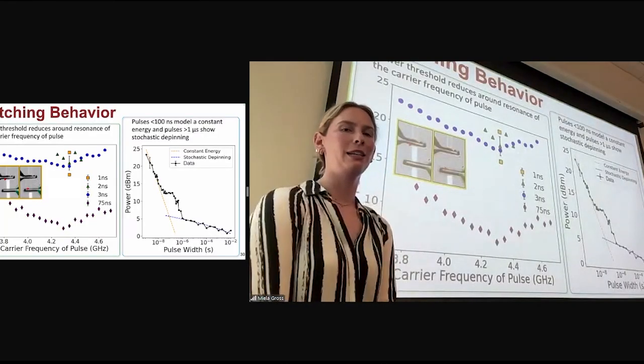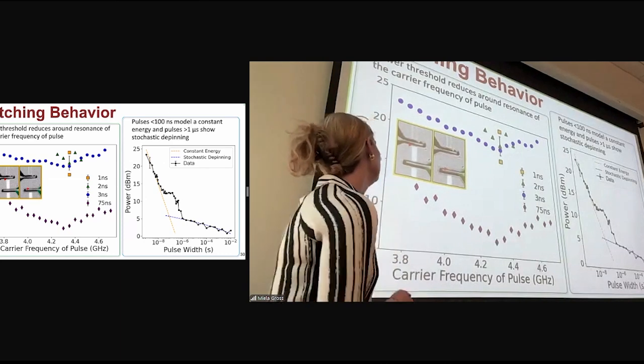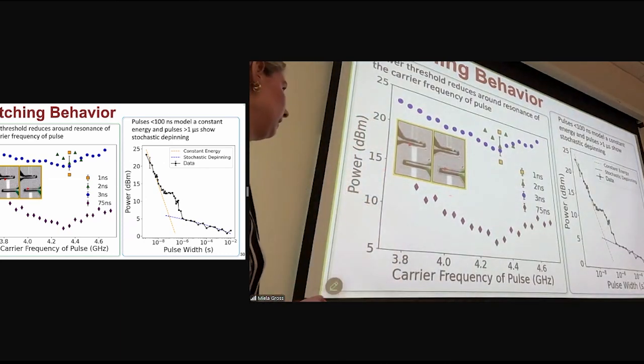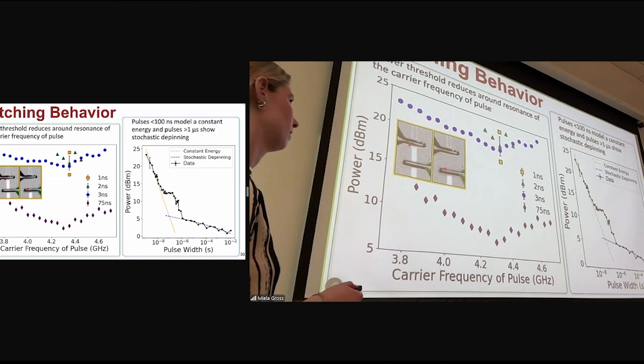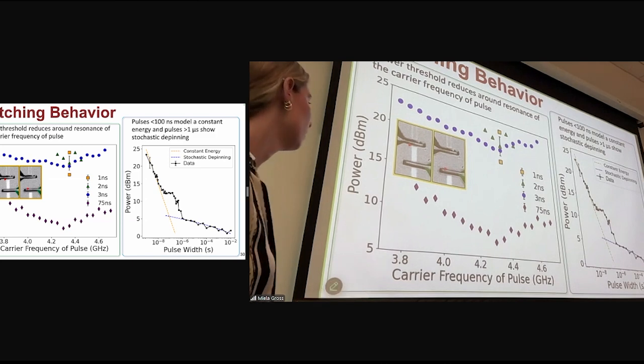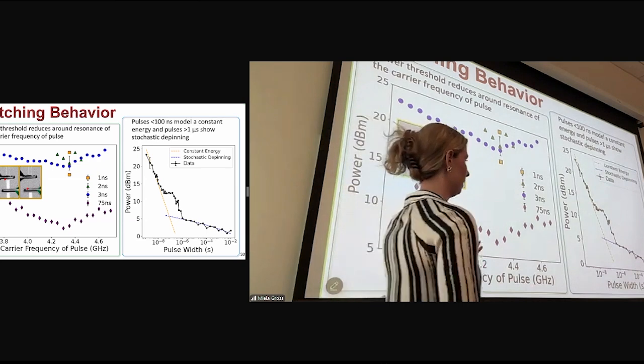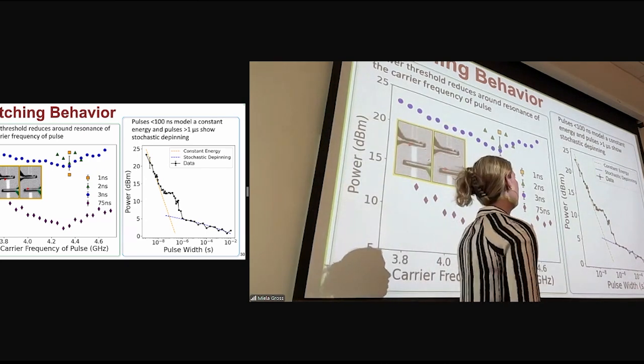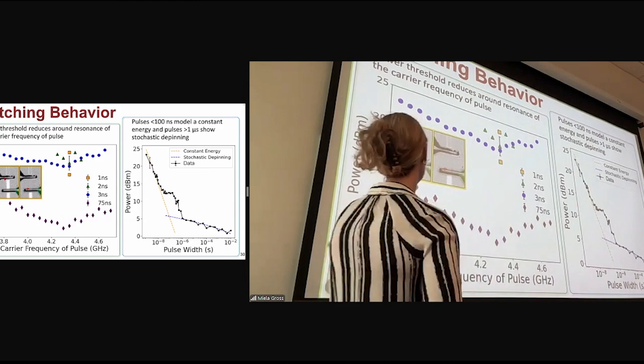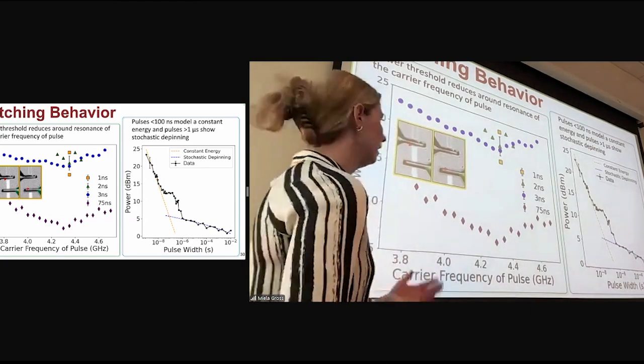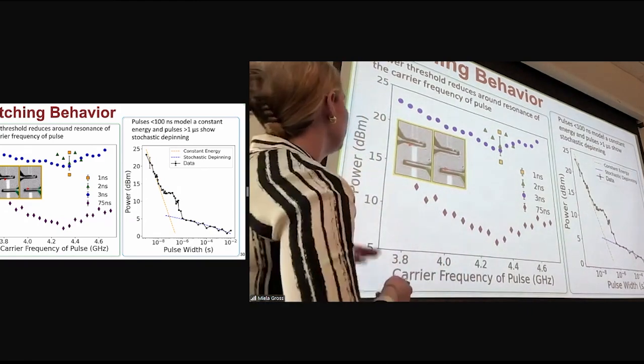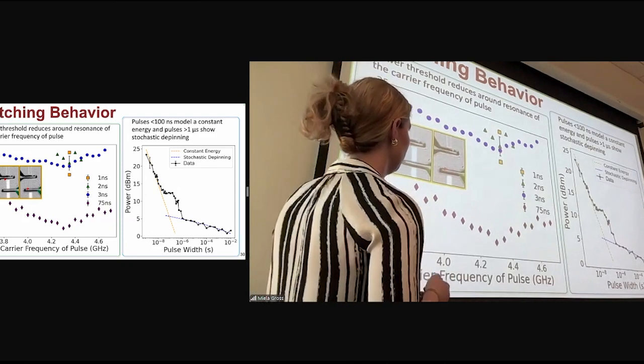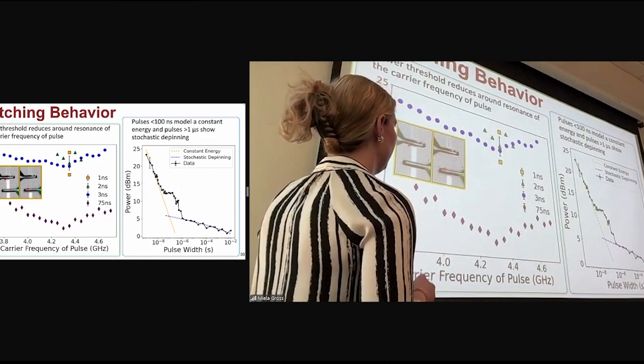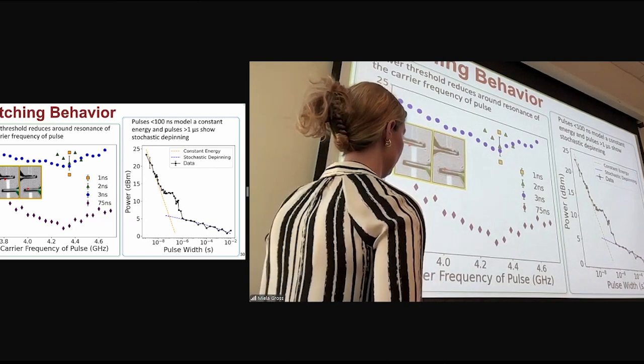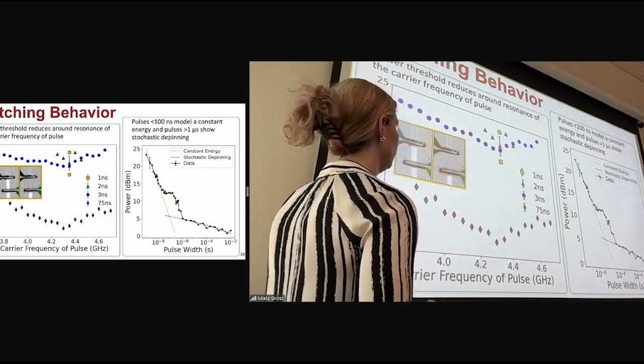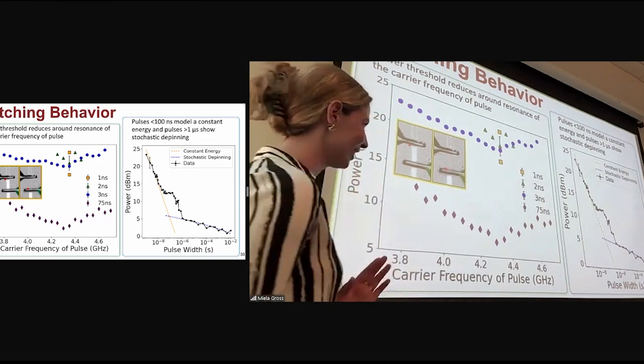So I want to look at some statistical switching behavior. This is on that same device, which is shown here, and that 1 nanosecond pulse corresponds to this little data point here. We wanted to look at how the carrier frequency of the RF pulses and the pulse width of those pulses changed the minimum power threshold needed to switch or move the domain wall in these devices. We can see in the plot on the left that for a 1 nanosecond pulse, the only frequency that actually moves the domain wall is its resonance, which is 4.35 gigahertz.